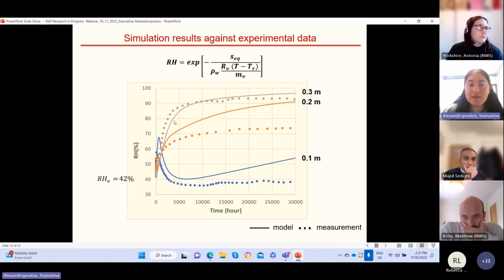In the next slide, in a similar manner, I'm presenting the results of relative humidity in terms of time. The relative humidity is calculated through the suction, which is actually the negative pore pressure. Just to mention here that this initial increase that we notice is due to temperature and vapor flow, because the vapor flow is migrating and then condensating, so it increases the relative humidity here. But as the heating progresses, the bentonite sample dries out, so that's why afterwards the relative humidity decreases. These results correspond to the point which is closer to the heater.